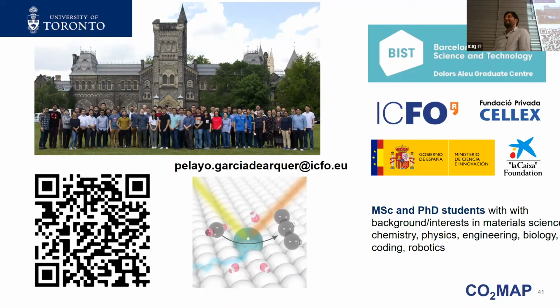Thank you, Pelayo, for a wonderful talk, really interesting. I would have many questions, but I would like to ask you about something that I have been discussing with many colleagues. For example, in most of your experiments, you combine an ionomer with an electrolyte, for example, at high alkaline pH. The pH of your bulk solution is 5 molar KOH, but the ionomer is acidic. So how is this changing the pH you are working at in your last example? Your model tells us that at high current densities, the surface pH is different. Which pH do you use to estimate the thermodynamic potential of the reaction? How can you do that?